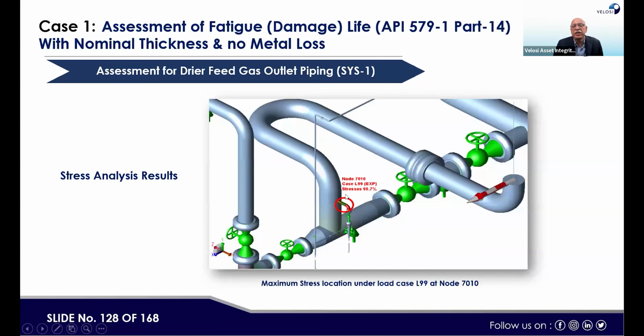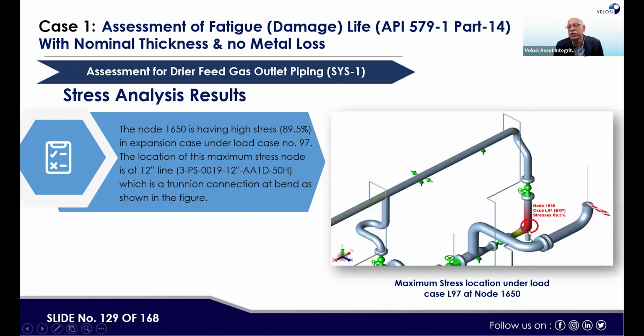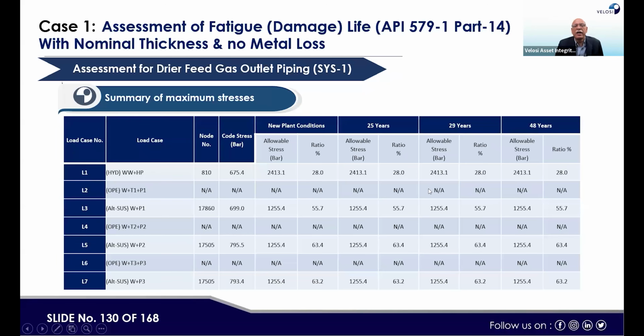So if you see, this is the piping along with the big pipe, there was a small pipe, right? This small pipe area was under high stress, and you can see that if a small bore connection is connected with a big pipe, it could be subject to fatigue stress and it may fail. This was shown. Similarly, at another area, this is a spot location where a high stress position is shown by Caesar 2. Since we are doing stress ratio first, interestingly, for 25 years, 29 years, and 48 years, the allowable stress ratio remains more or less the same, like 28% here, 28, 28. So there is no increase in stress in the stress analysis. But in fatigue analysis, you will see another kind of scenario.